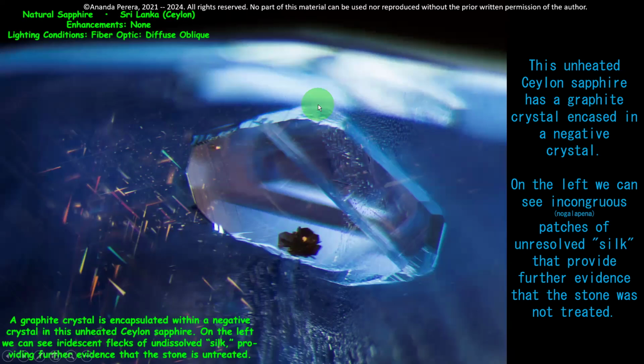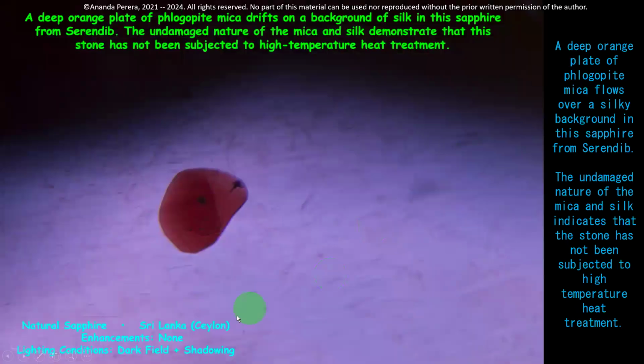Remember this. What is this? And what are the lighting conditions here? Dark field plus shadowing are the lighting conditions. Look at the environment and the color, not brown, deep orange plate of phlogopite mica. Phlogopite mica is there. It is a deep orange plate of phlogopite mica floating over a silky background.